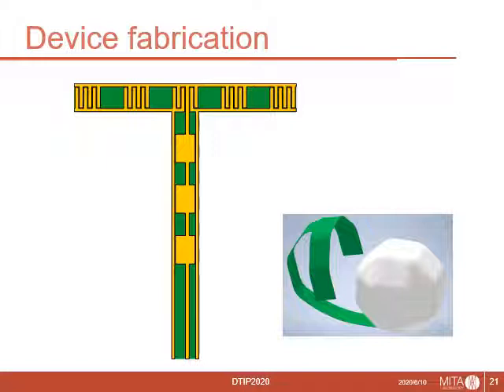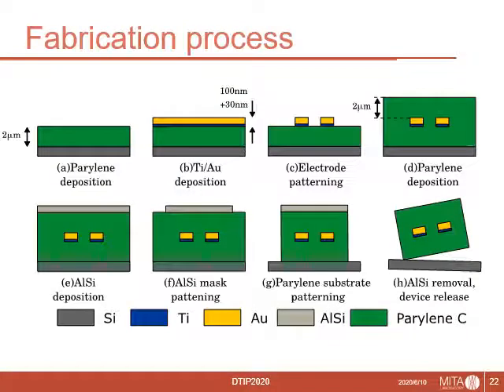Because we confirmed that the actuator was useful, we fabricated the flexible electrostatic connection device. This is fabrication process of our flexible device. First, 2 micrometer thick Parylene C was deposited on silicon substrate for handling. Next, 30 nanometer titanium and 100 nanometer thick gold were sputtered and patterned by wet etching. After the patterning, 2 micrometer thick Parylene C was deposited on top.